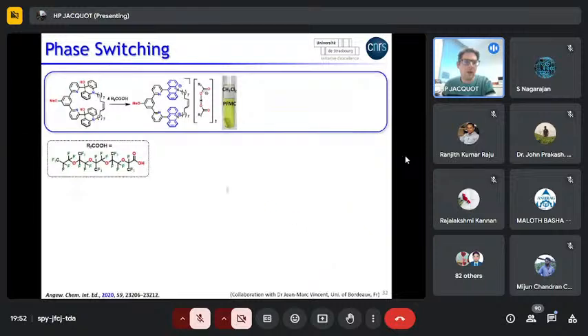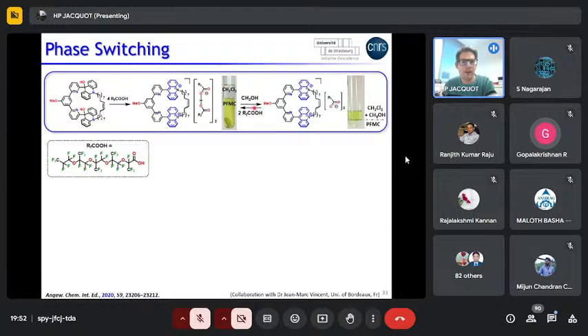So what we did is that we used our bisacridane macrocycle in the presence of the same highly fluorophilic carboxylic acid. And actually, it did two things. The first one was the rearomatization of the acridinium cores, the formation of the highly fluorophilic counterion that brought the molecule from DCM to the PFC phase. Then also, we have no leaching of the macrocycle into DCM. So if you want to have it back into an organic phase, what you have to do is just add a few drops of methanol that is going to act as an H-bond competitor for the counterion. So you will have a counterion which will be less fluorophilic, only the carboxylate counterion, and this time the molecule goes back into the organic phase.